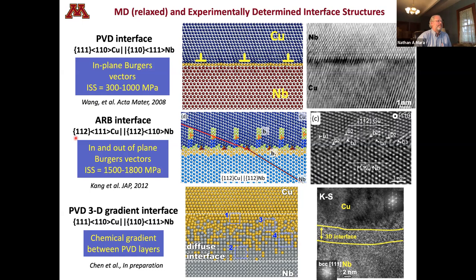We compare that to the ARB interface that we just talked about, much higher interfacial shear strength, but also has out-of-plane Burgers vectors. And then we're going to compare those to this 3D gradient interface, which has the same orientation relationship and interface plane as the two-dimensional PVD interface up at the top. But now we're going to put in a chemical gradient, which also turns out to be a structural gradient between the two phases. And this is actually a paper that's now been published in Acta Met. But you start seeing, again, very, very different mechanical behavior in this case.